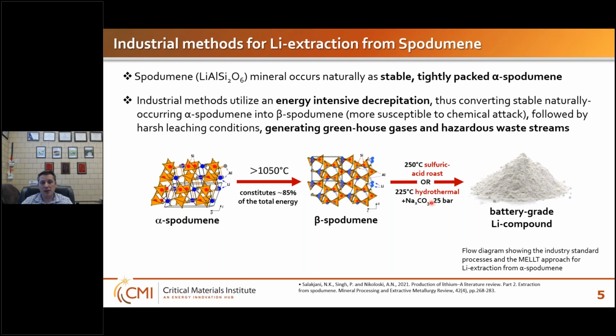So at the larger scale of 250 grams, we have demonstrated that we can extract around 75% lithium out of spodumene. This work is still in progress, and the target for industry is more than 90% extraction yield. So we are optimizing our process to still reach that. Anyhow, with this partial scale up and partial extraction yield, our industrial partner Piedmont Lithium performed a preliminary techno-economic analysis. For this, we compared the industrial process, which is sulfuric acid roasting, with our MELLT method.